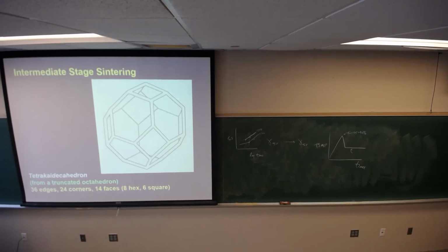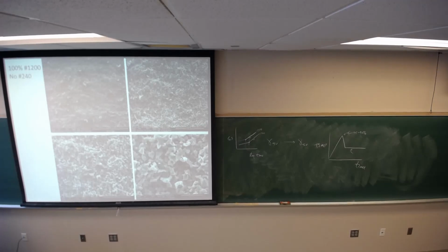But I'm going to show you this intermediate stage sintering. They draw these really neat drawings, but I have an image here. There we go. This is sintered silicon carbide, and this is one of the best examples of that intermediate stage pore forming where you get a cylindrical pore that connects basically all the pores together. Really remarkable microstructure and a difference from this. This is also obvious to have that sort of pore structure.